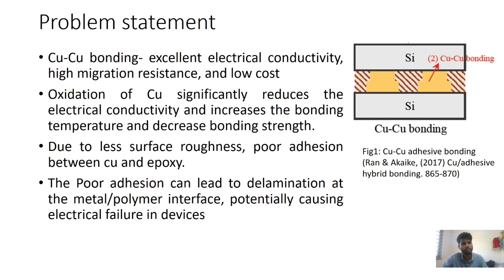I am Deepak and today we discuss the topic of adhesion improvement of copper and copper epoxy joints. In the past few decades, silicon is the most widely used semiconductor material for power devices, and we attach the silicon die with tin based solders. But for high power applications, we use wide band gap semiconductor materials such as silicon carbide and gallium nitride. At the junction of wide band gap chips, the temperature may reach about 250 degrees centigrade, and at that temperature, the tin base solders may melt.